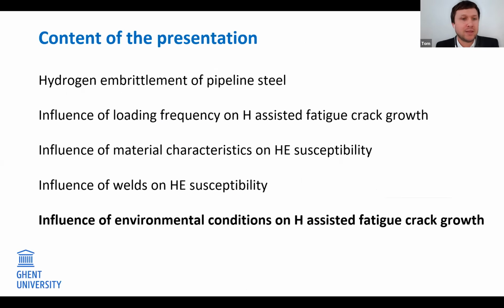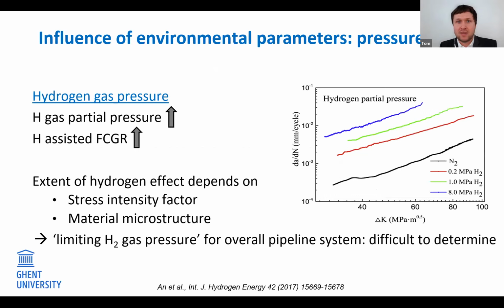Let's go to the final influence, the influence of the environmental conditions on hydrogen-assisted fatigue crack growth. Let's start with pressure. As the amount of atomic hydrogen available per unit volume increases, the localized hydrogen embrittlement effect at the tip of a growing crack is also increased. This is because the hydrogen trap occupancy is a strong function of pressure and exhibits a plateau behavior as the traps saturate. An increase of the fatigue crack growth rate with rising hydrogen partial gas pressure is observed in the graph.